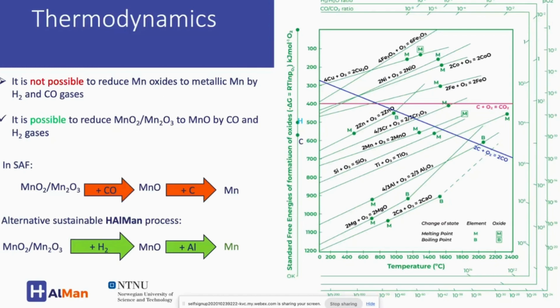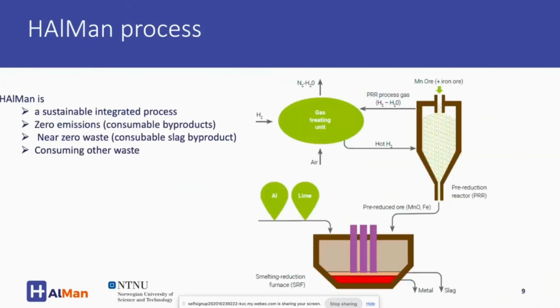So if we look at this, we don't have a direct CO2 emission from the HAlMan process. Next slide, please. Here you see a schematic of the process. What we do is that in the process we use hydrogen. It's preheated. We get hot hydrogen and it's used in a reactor to produce pre-reduced ore.